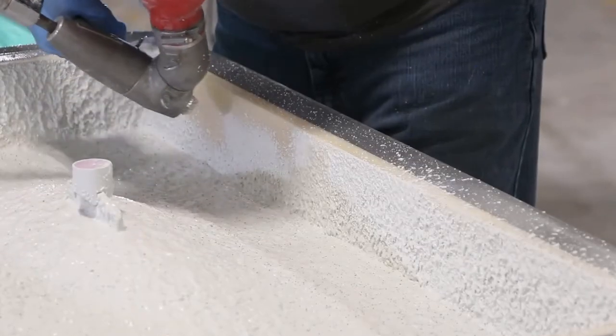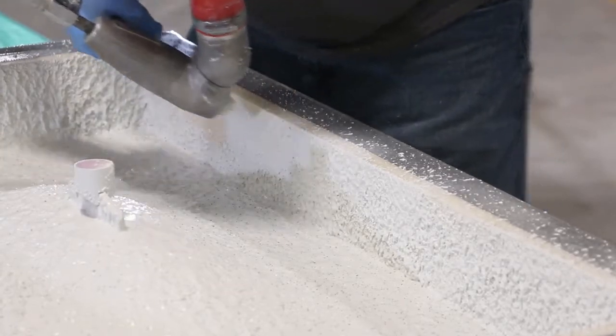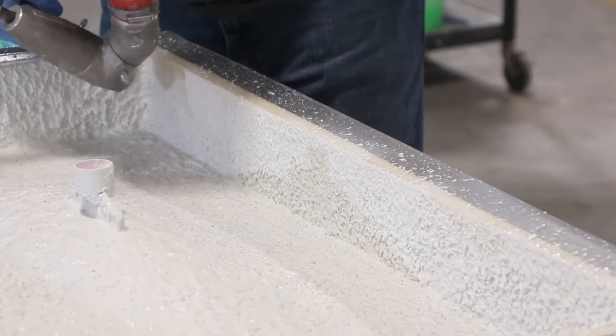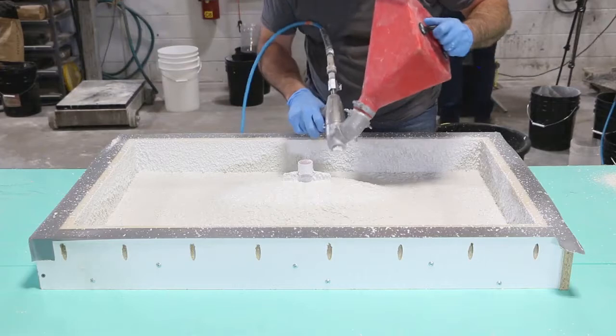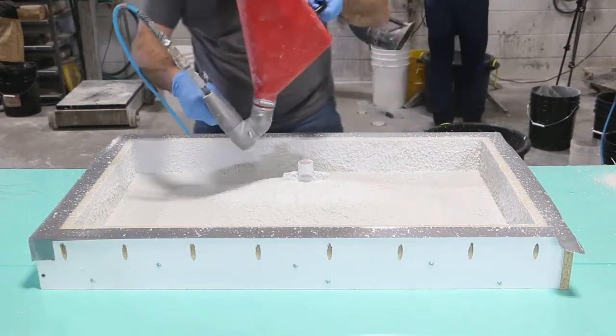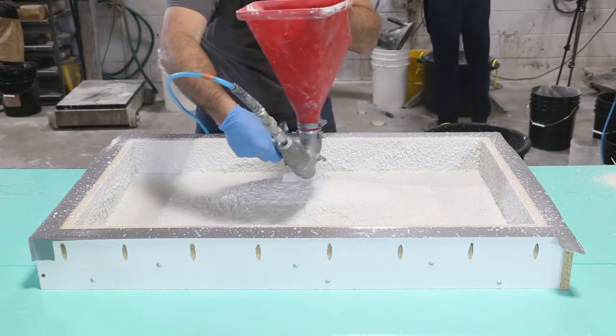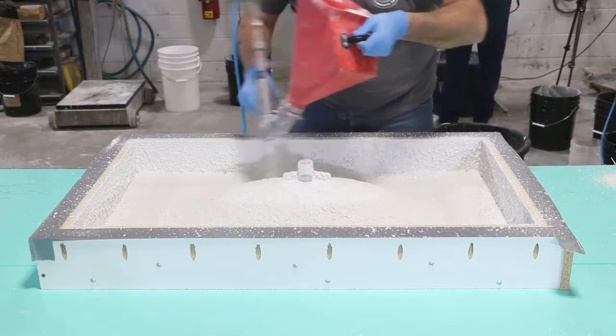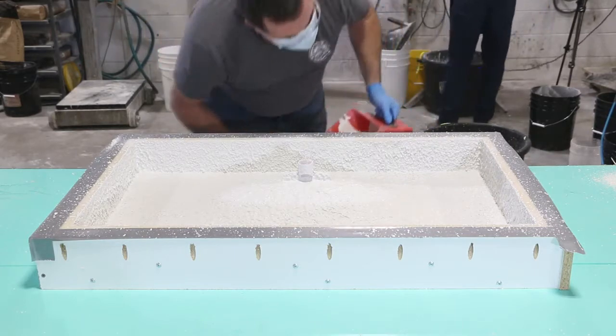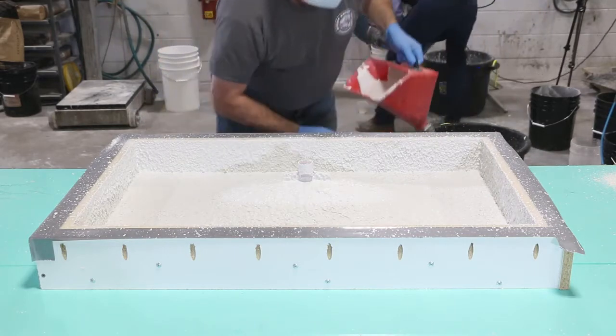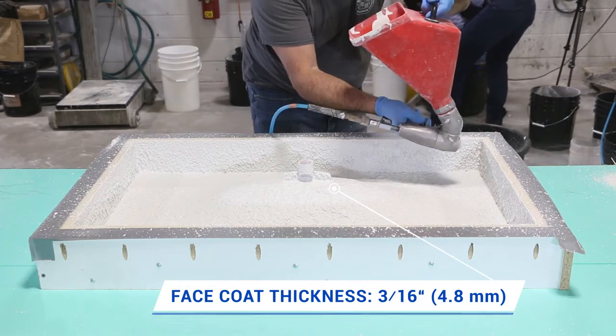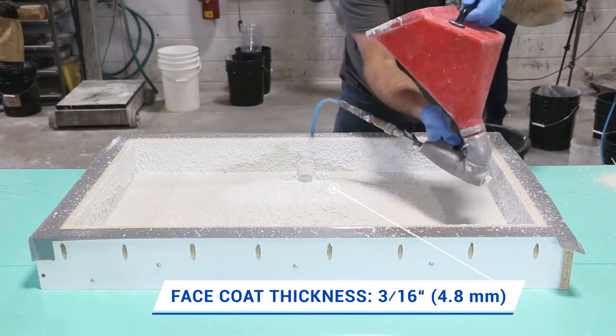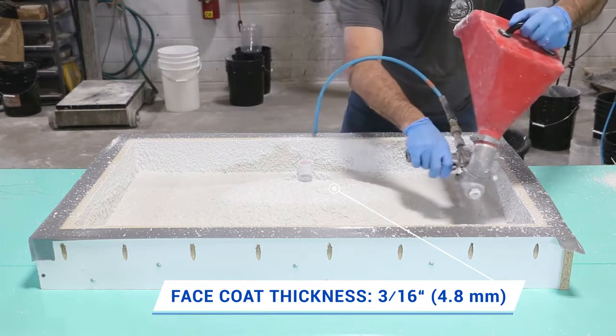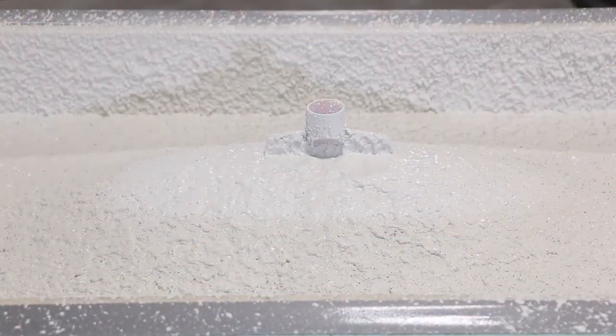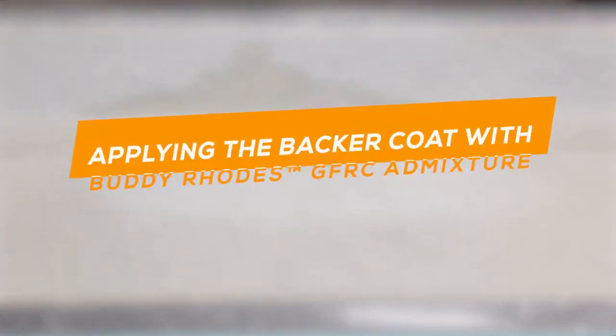This style allows for some minor voids randomly created on the cast surface, which are easily filled and give more character to the casting, embracing concrete's organic visual texture. Once the entire surface has been sprayed, go back and check for any lighter sprayed areas while building a little more over the entire area. The prescribed face coat thickness should be approximately 3/16 of an inch. At this point, I was ready to begin mixing the backer layer.